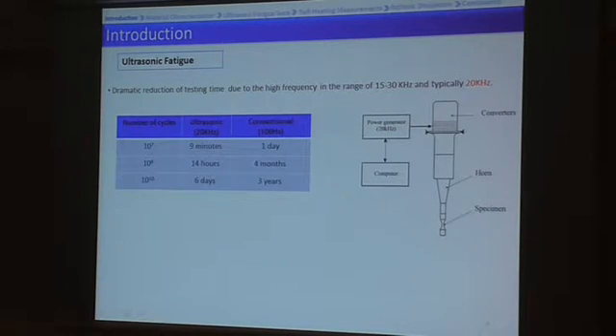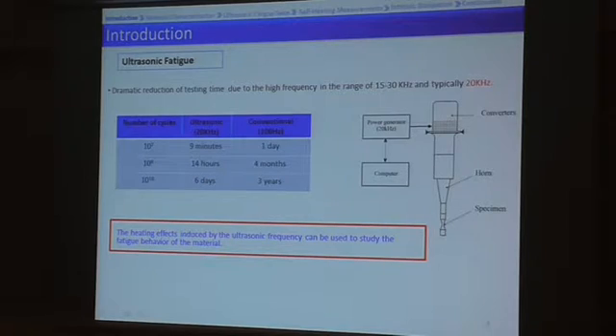Ultrasonic fatigue loading is an effective tool to do high and very high cycle fatigue tests. I will not explain more because we had enough explanations during the invited lectures, and I just mentioned that we can use the heating effects induced by the high frequency to study the fatigue behavior of the material. Actually, this work is not directly related to fatigue crack initiation rupture, but the heating measurements can help us study the fatigue behavior of the material.